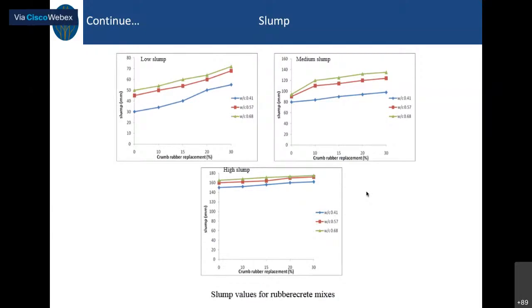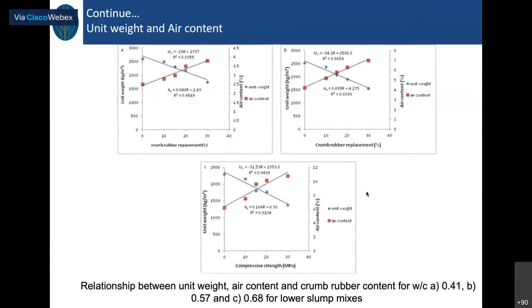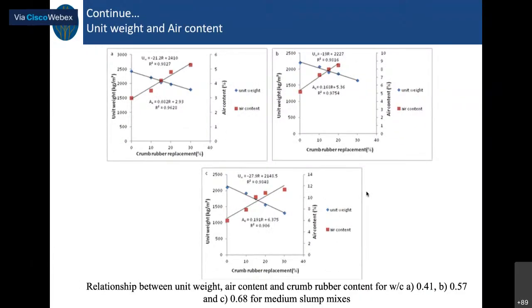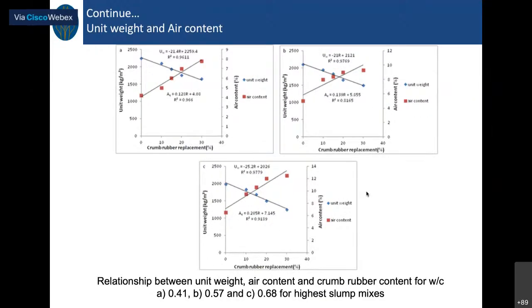And this one, some of the data on the slump, you see the slump of the rubbercrete actually improves. So if you have a problem with the slump of the concrete, you can use some amount of crumb rubber replacement, like 5%, to improve the slump without increasing the water ratio, because the water ratio leads to a decrease in strength. This one I just skip.